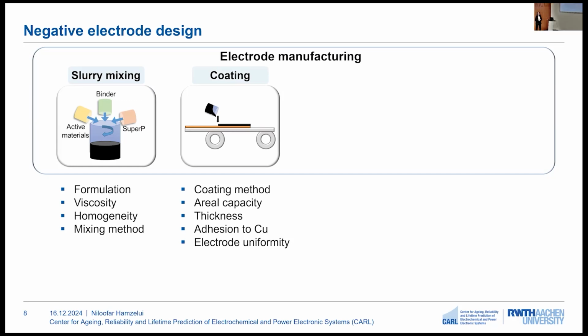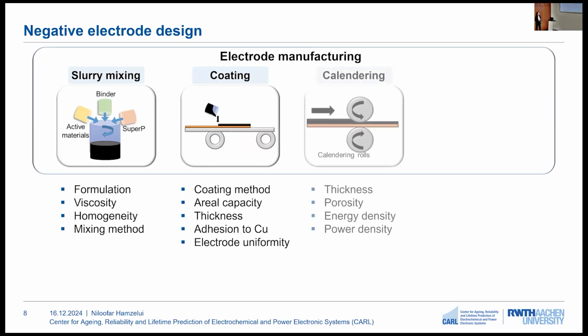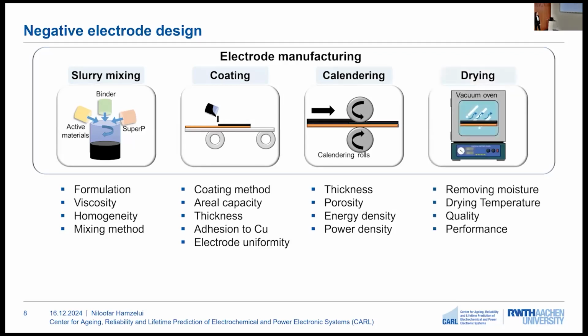The adhesion to the copper foil and the uniformity of the electrode is of high importance. The next step would be calendaring the electrode. Here we can control the thickness and porosity. And then finally, before using the electrodes in a battery, they need to be dried under vacuum to remove the